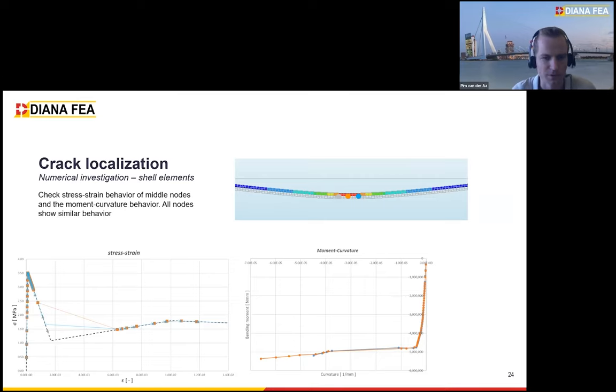So then you will always find the same bending moment curvature diagram for all the points in your shell model. And on the left side, you can actually see that the stress-strain relationship for all the points is nicely respected, because you can see that all the points are on the black dashed line. And the points, of course, are connected with individual lines, but they do not represent the actual behavior. But you can see that all the points are nicely on the stress strain, which has been used as input.